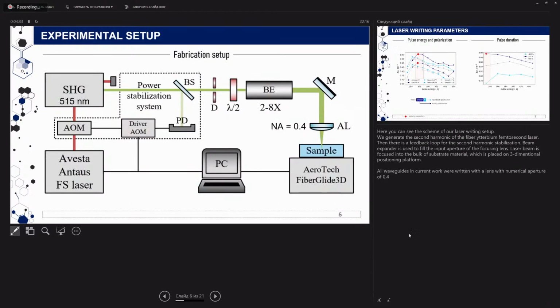Here you can see the scheme of our laser writing setup. We generate the second harmonic of the fiber ytterbium femtosecond laser. Then there is a feedback loop for the second harmonic stabilization. A beam expander is used to fill the input aperture of the focusing lens. The laser beam is focused into the bulk of substrate material, which is placed on a three-dimensional positioning platform. All the waveguides in the current work were written with a lens with numerical aperture of 0.4.